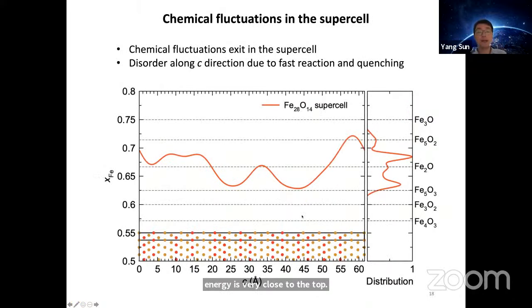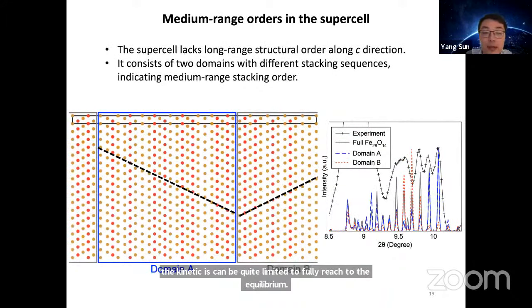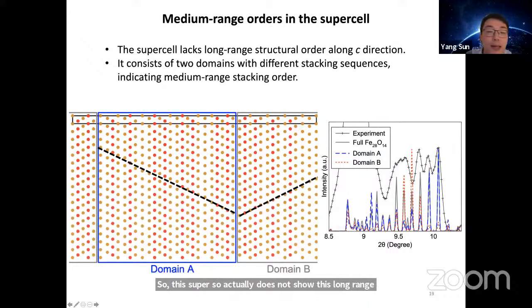To further understand this large supercell, we analyzed its chemistry and structure. As you can see, while the overall composition is 2-1, it actually has very strong chemical fluctuations along the c direction. This is quite related to the experimental conditions: it was synthesized at high temperature with very short laser heating, and the cooling process was very fast. So the kinetics can be quite limited in fully reaching equilibrium. This supercell does not show long-range structural order along the c direction.